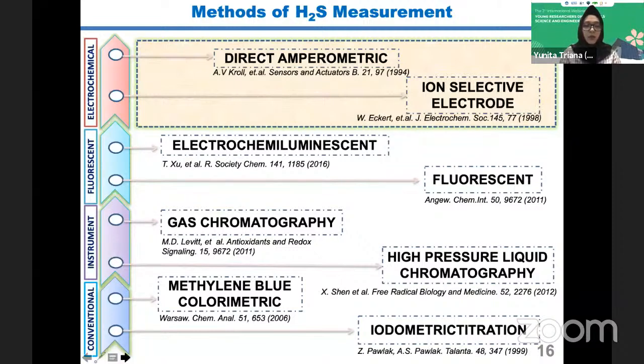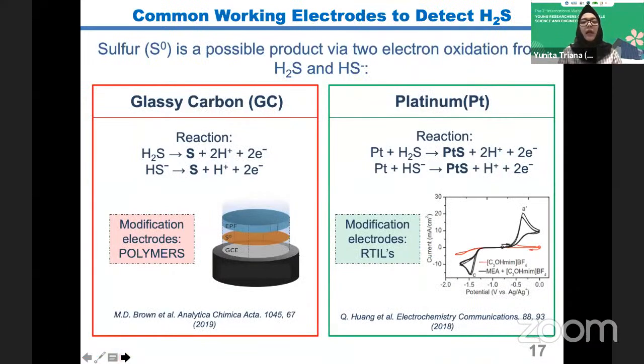So next, what is the common electrode to detect H2S? The common electrodes are glassy carbon and platinum. Usually on glassy carbon, H2S causes sulfur fouling on the carbon surface, so they should modify the glassy carbon using polymers. In this paper, they use a polymer-modified electrode to prevent the sulfur fouling.